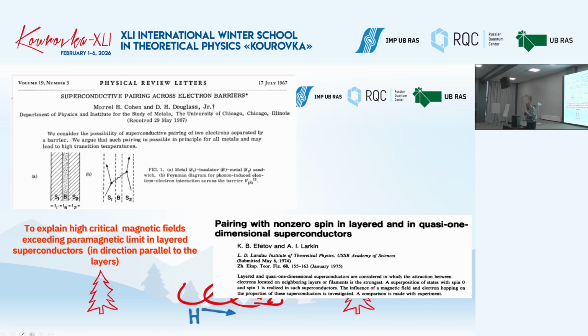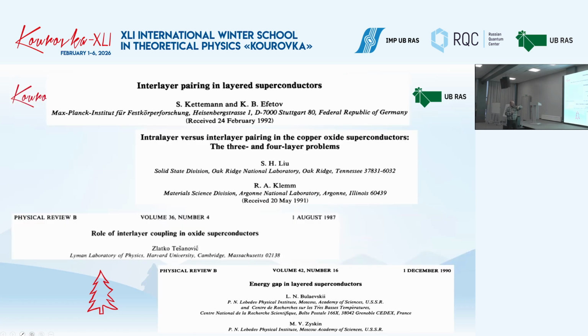But triplet pairing is much better because in this case we do not have such a restriction, and we can have a rather high critical magnetic field. This was in fact the idea suggested by Efetov and Larkin. They said, if we have this interlayer pairing in a layered superconductor, we can have triplet pairs, as I tried to explain, and then we can have very high critical magnetic fields. Then this story continued in many works, in application to high-Tc cuprates and so on.